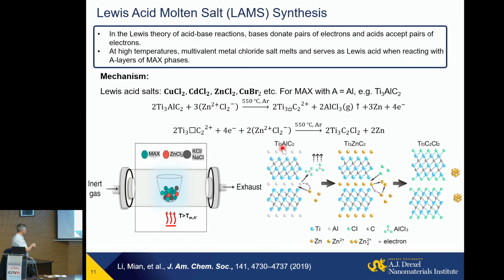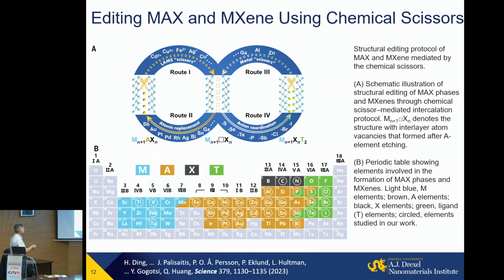And the most developed one is the one which uses various types of chloride or bromide salt, usually in a mixture, where you can replace aluminum with, for example, zinc or another metal which is easily etchable. And after that, you can remove this metal and get chlorine, bromine, iodine surface termination, and get a material with different properties. Moreover, working with Professor Qing Huang, who initiated this approach, and our collaborators in Sweden, we showed this is a very, very universal approach.